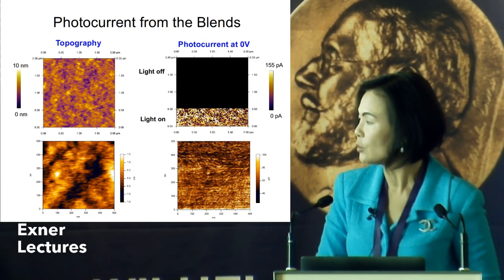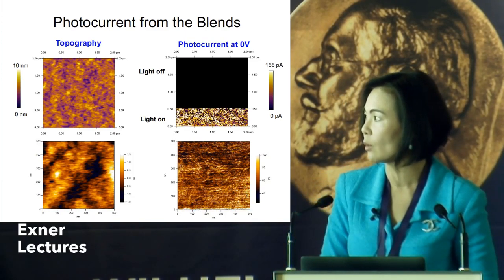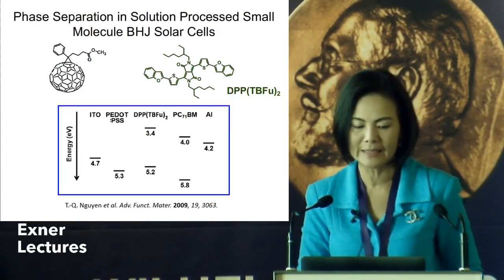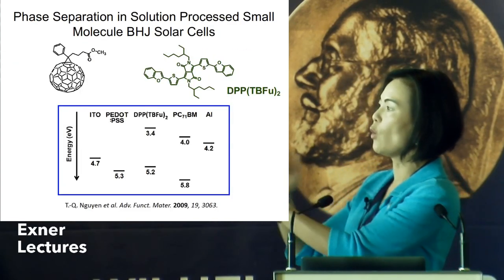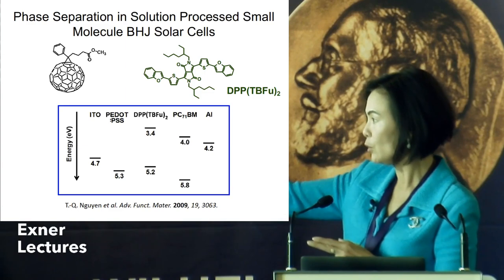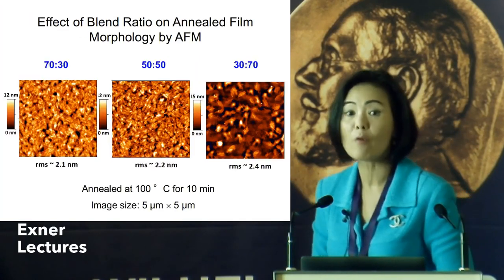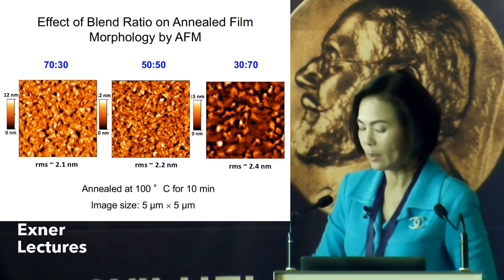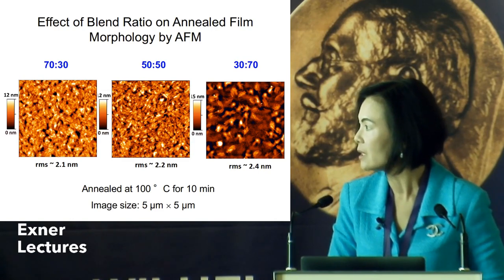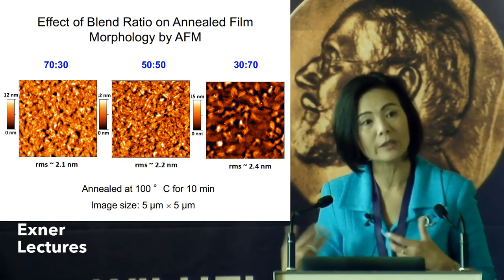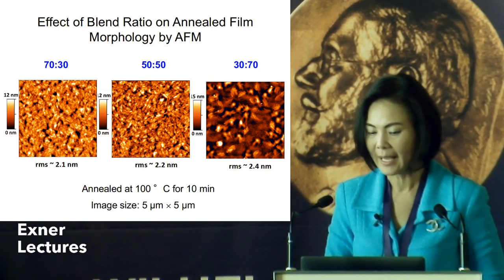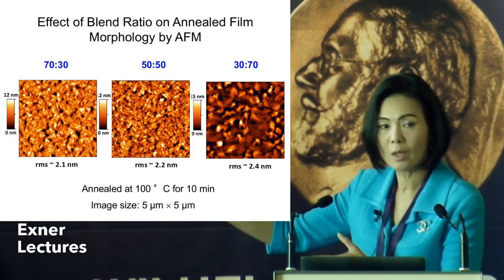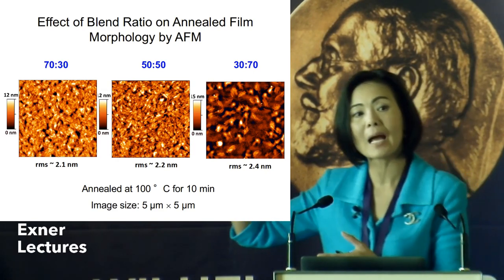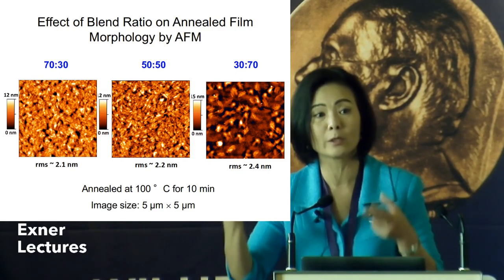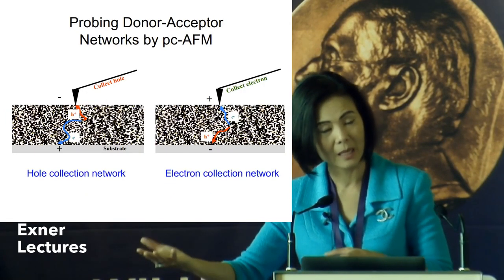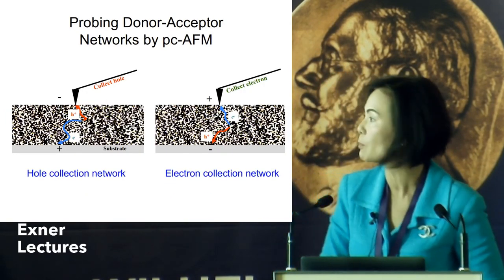So then we use that to try to characterize solar cells, for example, such as the one here. When you change the donor-acceptor ratio, we do see a change in the surface morphology, but we do not know whether the feature you see here is actually the donor or the acceptor domain. By applying the tool, we can selectively map out the photocurrent generated by the donor or by the acceptor, which allows us to assign the phase separation.